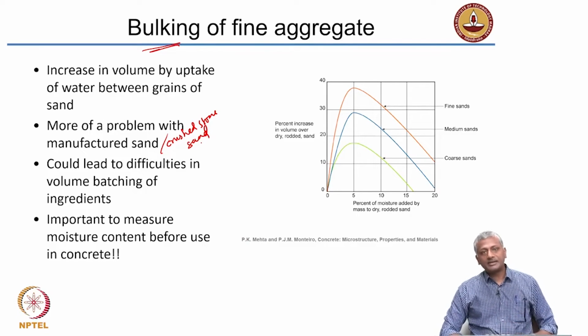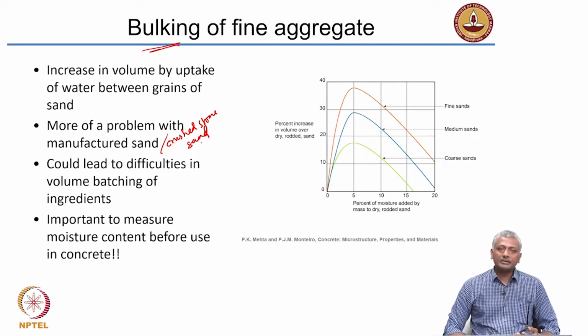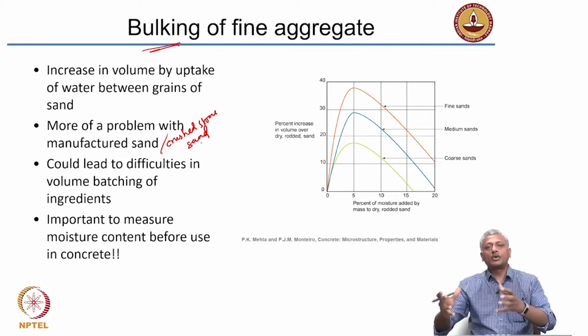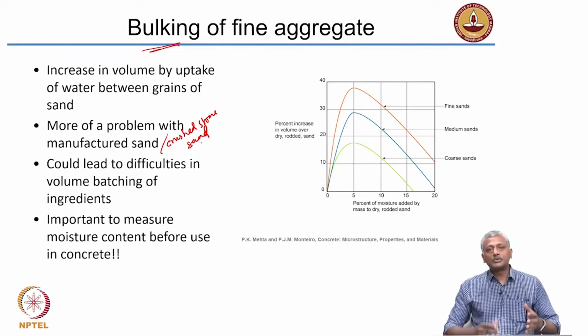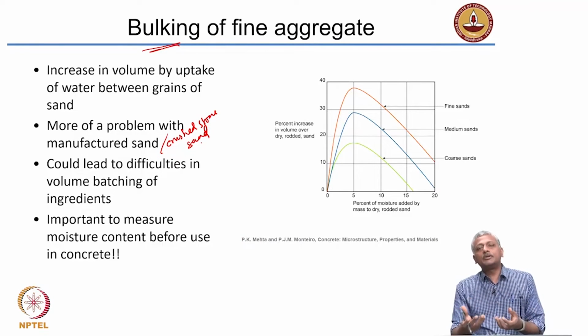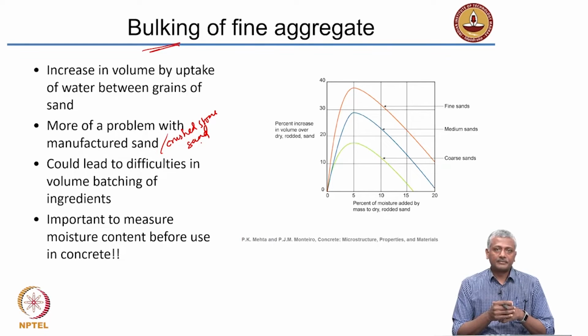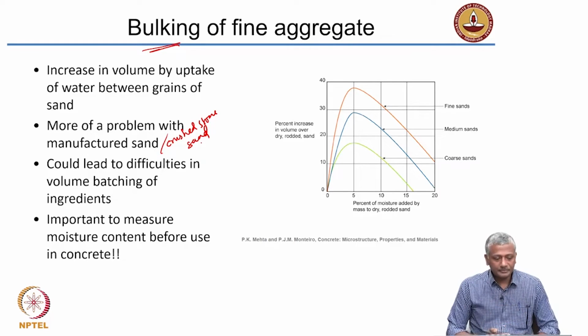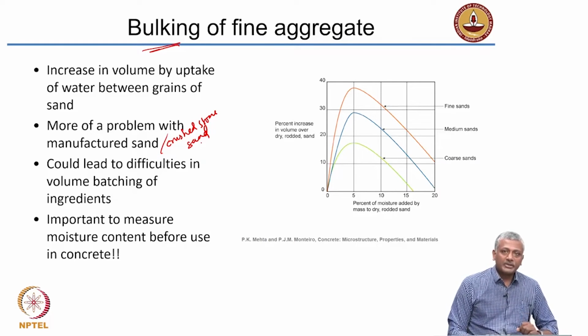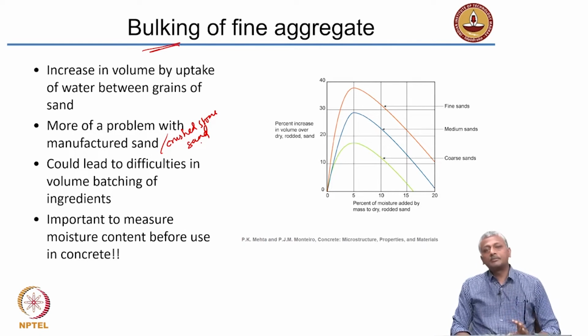Now, one thing I must say is that this is truly a big problem only in the case of concrete where you do volume batching. That means you are measuring quantities by volume. If you are measuring by mass, all you have to do is dry this mass of wet sand and determine how much water is actually inside. Okay, that way you can get the exact mass of the dry sand and the mass of the water properly input into your concrete mix. If you are checking volume, then you have a problem. Okay. So, it is important to measure the moisture content of the aggregate in concrete, because that ultimately leads to a lot of hassles at the job site.